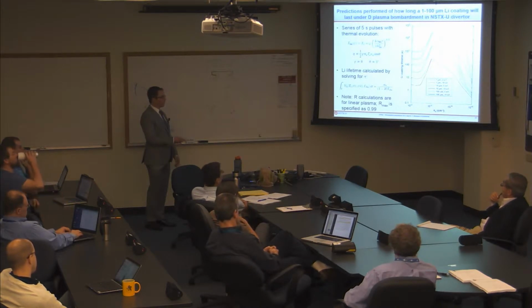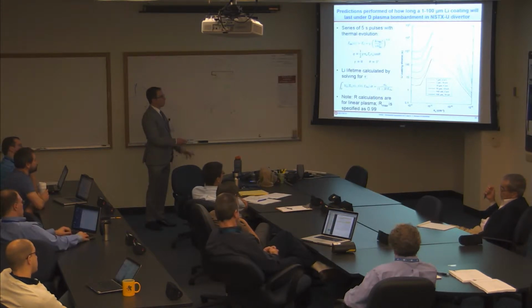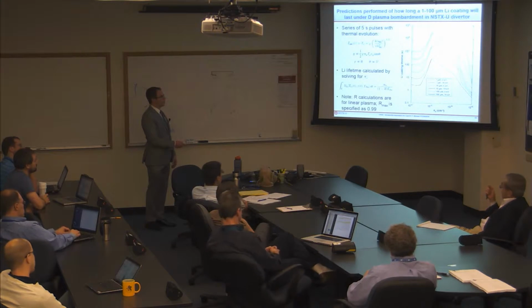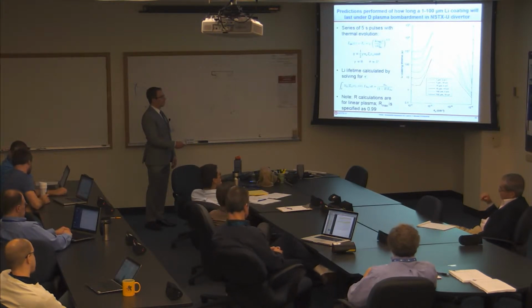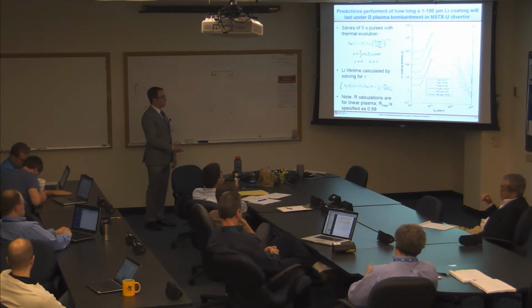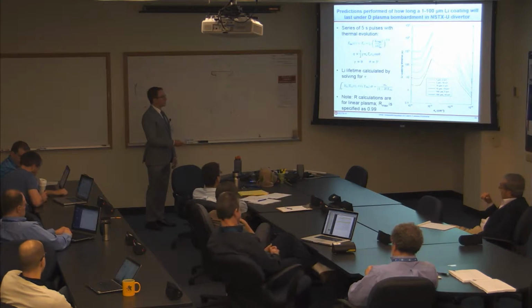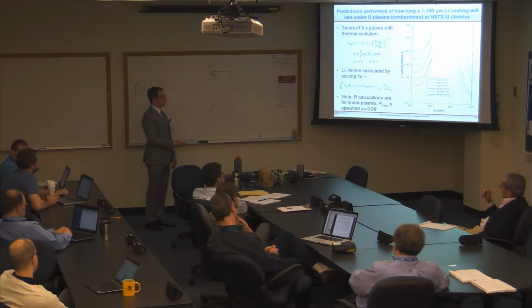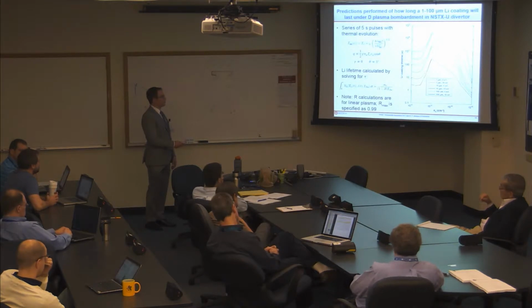And the other thing you have to think about: here you're in the quote-unquote linear regime, where the redeposition fraction is already 0.99, so it's already maxed out, and then it basically decreases linearly because the density is increasing. You basically expect the erosion rate to be proportional to density because it's proportional to the flux.